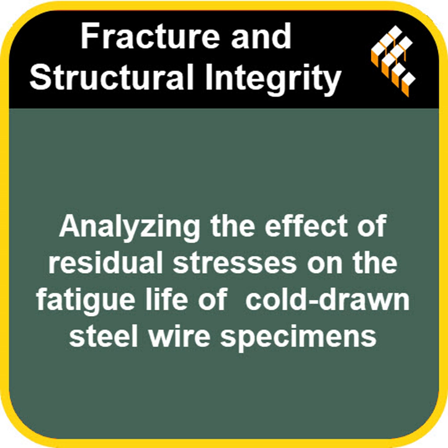Okay, let me make sure I get that. So it's not that the material got intrinsically tougher, but the effective stress it actually experienced during the fatigue test was lower. Precisely. Imagine the applied tensile stress trying to pull the material apart, but there's this built-in compressive stress already squeezing it together. The net effect is a lower overall tensile stress doing the damage. Like an internal shock absorber, sort of canceling out some of the bad stress. That's a good way to think about it. It reduces the peak tensile stress that drives fatigue cracks.